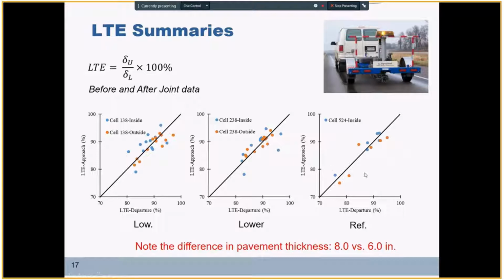On the right graph, I have the LTE data obtained for the reference cell, cell number 524. We can see a couple of measurements with LTE values lower than 80%, somewhere like 75 or 76%. But we should note that the reference cell had a thickness of only 6 inches compared to 8 inch for the experimental sections, so I would say good performance for this cell as well. We also had a 1 inch diameter dowel in this cell. Overall, we have comparable performance and acceptable LTE values for both experimental sections, regardless of the binder content, whether it's 470 or 500.